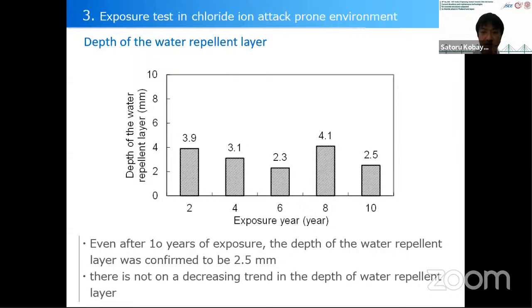This is a measurement result of the depth of the water repellent layer. Horizontal is exposure year, vertical is depth of the water repellent layer. Even after 10 years of exposure, the depth of the water repellent layer was confirmed to be 2.5 millimeters. Also, there is no decreasing trend in the depth of the water repellent layer. In other words, even though the water repellent condition could not be confirmed like before, the water repellent layer is still existing in the concrete, absolutely.